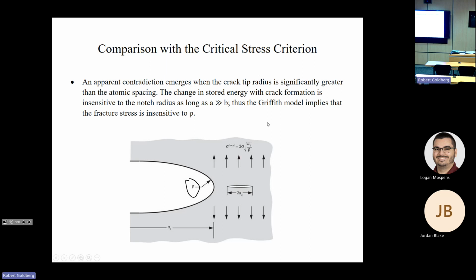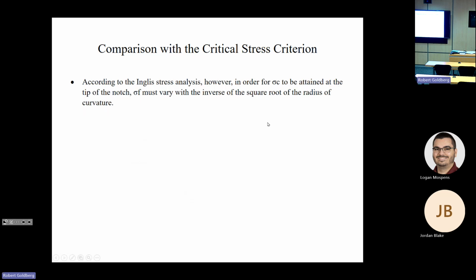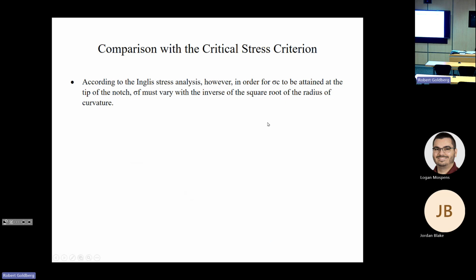And the Griffith model implies, because we don't have anything in either the sharp crack or a penny-shaped crack talking about the atomic radius, that the fracture stress is insensitive to the radius of curvature. But according to the Inglis analysis, for the cohesive stress to be obtained at the tip of this notch, the Inglis criteria specified that the local stress at the notch tip is equal to twice the applied stress multiplied by the square root of the ratio of half the crack length to the radius of curvature.